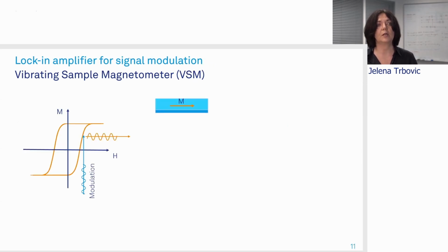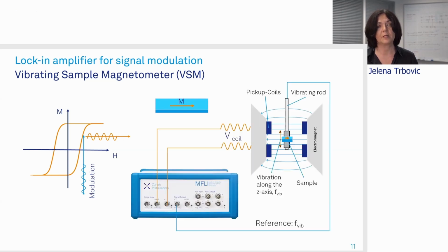And this is exactly where the Lock-in Amplifier comes into play, because we can then modulate the signal coming into the system and read out the outcome, which is proportional to magnetization. And in a typical VSM system, that Yury will talk about in greater detail, this is done such that the Lock-in Amplifier is providing the reference to the VSM rod where the sample is vibrating in the homogeneous magnetic field. And these vibrations induce the voltage in the pickup coil, which is also proportional to magnetization, and we can measure them differentially using the Lock-in Amplifier.